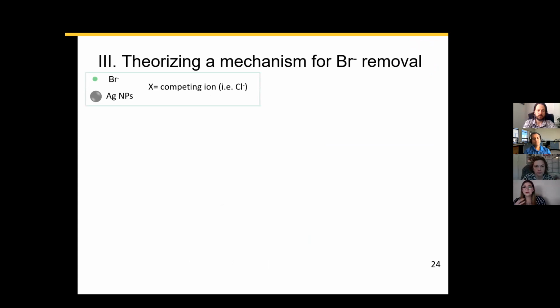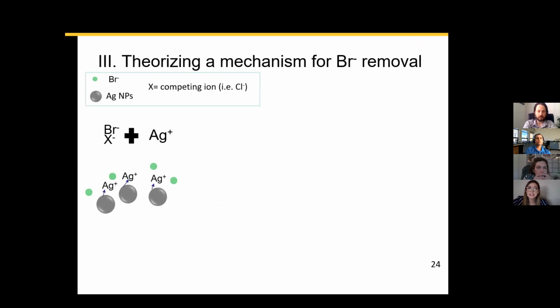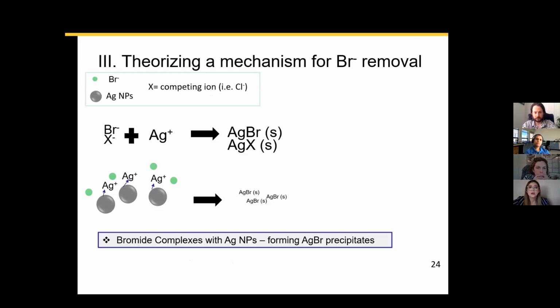So let's talk a little bit about what's happening. We have theorized two main mechanisms to remove bromide using the silver composites. The first one is, let's suppose we have bromide present in water. Upon the addition of silver nanoparticles, we know that the silver nanoparticles can start dissolving into silver ions, which will then form the silver bromide precipitates.